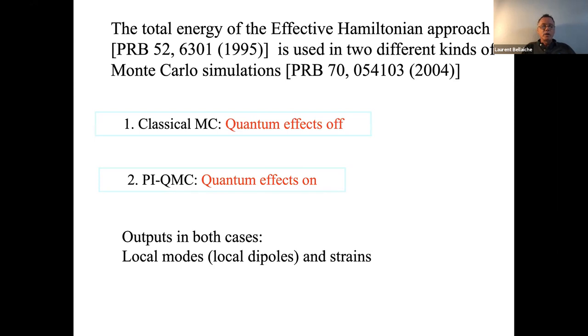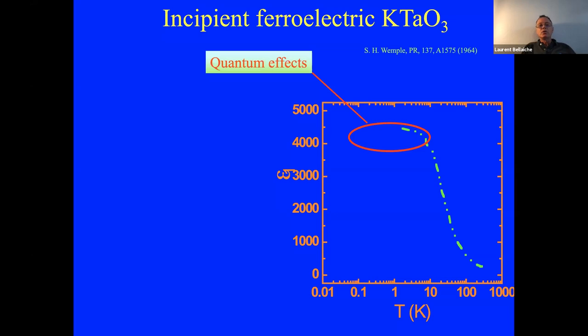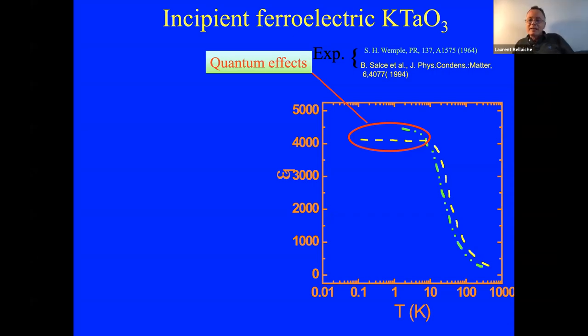And in both cases, we got local modes, we got strain, we got dielectric response. So let me show you the result. These are experimental data. This is how the dielectric response versus temperature looks like in potassium tantalate. You see this huge value, 4,000, at low temperature. There is another experiment that shows the same thing there. And then we started our simulations.